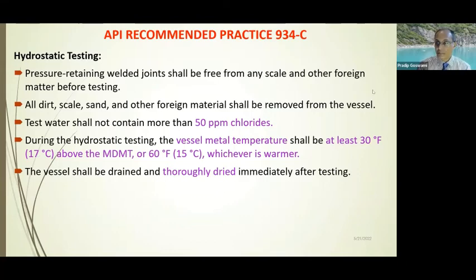Just a minute, please. Shall be at least 30 degrees Fahrenheit or 17 degrees centigrade above the MDMT, or 15 degrees centigrade or 60 degrees F, whichever is warmer. So that is a very specific requirement, and generally speaking, I would say that this particular requirement, 15 degrees centigrade, keeps the thing very clean and straight. And the vessel shall be drained and thoroughly dried immediately after testing.